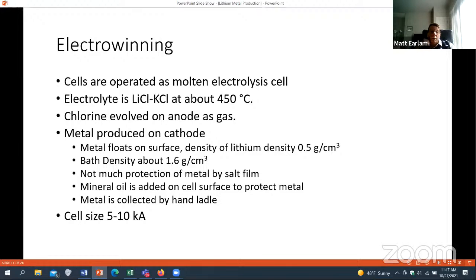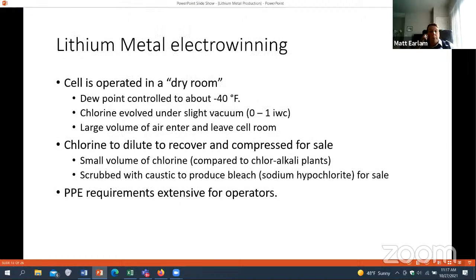It's a tremendous amount of air that has to go through the process because we have to remove the chlorine gas from the operators. And we want to remove chlorine gas as soon as possible to cut down on any recombination of the chlorine with the lithium. So as I said, they operate in a dry room. The dew point's kept at about -40 Fahrenheit. And the chlorine is evolved under a slight vacuum, under the cover of about 1/2 inch of water column suction. That's enough to move the chlorine away, but not so much that it sucks in so much air from the dry room that you just can't keep up with it.